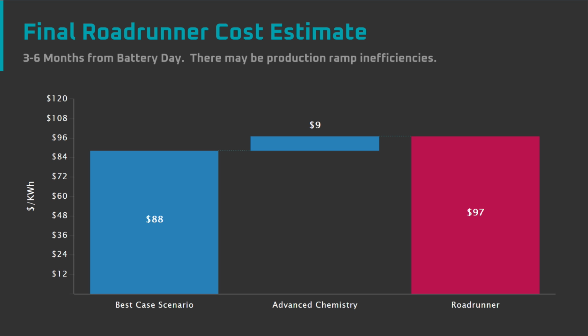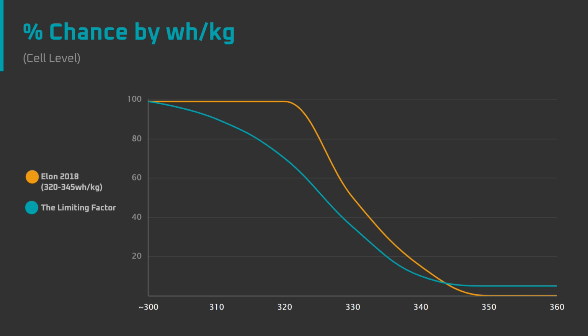Cost aside, what about energy density? My estimates remain unchanged from the original series, and I'll provide a quick refresher to explain the curve of the chart. If Tesla uses the million-mile chemistry, they would hit close to 300 watt-hours per kilogram. If Maxwell technology allows for larger amounts of active material, this would bring the cell up to 315 watt-hours per kilogram. A larger cell might increase energy density further to 330 watt-hours per kilogram. If Tesla increases the silicon loading by a modest amount, the cell will max out at 340 to 345 watt-hours per kilogram. All of these happening is unlikely.